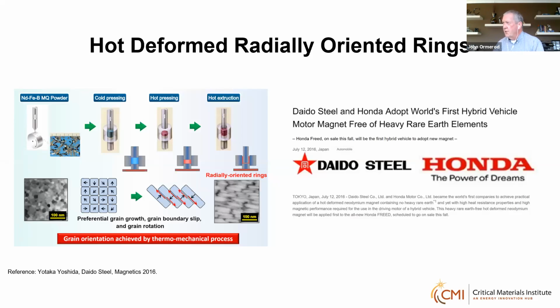And the other interesting thing to note is there is no, at least they claim there is no, heavy rare earth element content in these magnets, even though the traction motors obviously have to operate at elevated temperatures, certainly in excess of 150 degrees C.